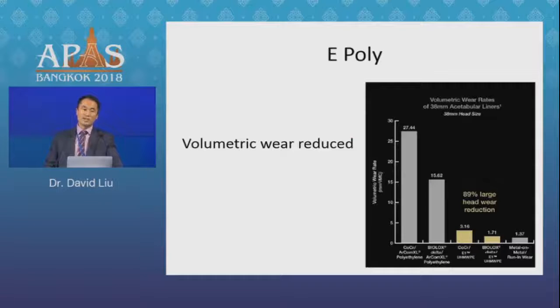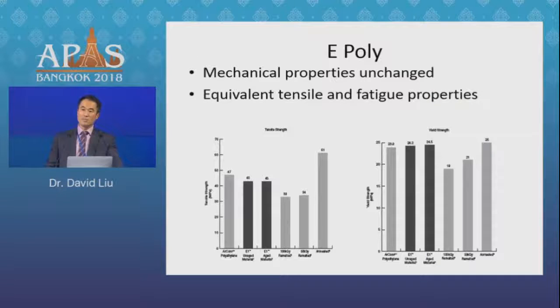And there's no doubt that simulator studies show that vitamin E poly has very good wear characteristics. We're approaching wear rates close to hard-on-hard bearings, and it certainly seems to be better than even some other second-generation cross-linked polys. Whilst at the same time we maintain its mechanical properties, it has much better tensile strength than the melted polyethylene, and similar sort of yield strengths to your annealed poly. So we're again maintaining the mechanical properties of non-heated polyethylene.